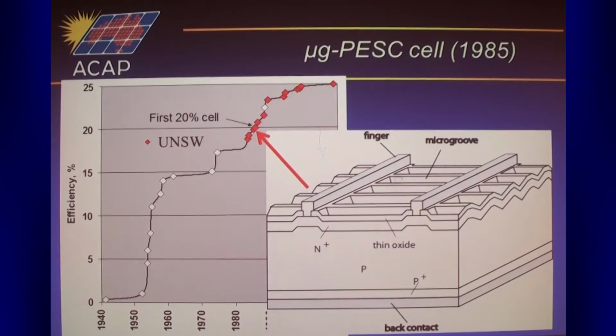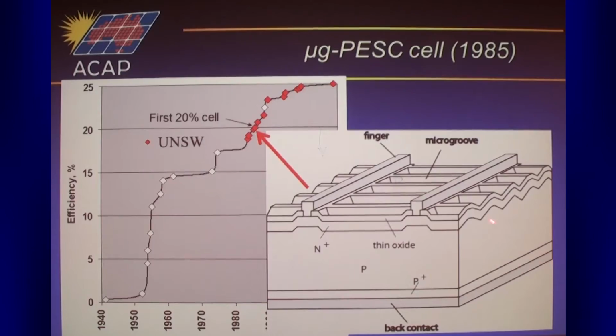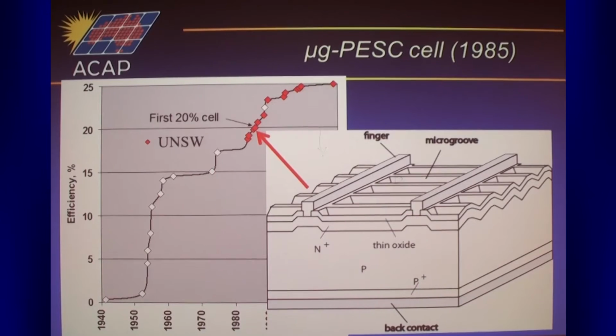The next big jump was by introducing texturing. So all those little pyramids that in a standard approach don't work well. Well, we had trouble making them work with the photographic approaches that we're using to define a lot of the features here. So we worked with more controlled structures. In this case, we worked with what we called slats or microgrooves. So these are formed by the same crystal planes in the silicon, have the same angles and everything, but we just confine them to, I guess, a 2-dimensional structure rather than a 3-dimensional.